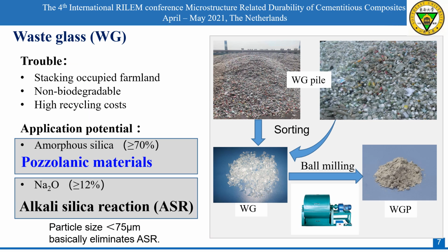Waste glass has brought some troubles to the society, such as stacking occupied farmland, non-biodegradable, and high recycling costs. Being amorphous and containing large amounts of silicon, glass should be an excellent pozzolanic material for the concrete industry. Therefore, when glass is finely ground to powder, in theory, it could be used as partial cement replacement.